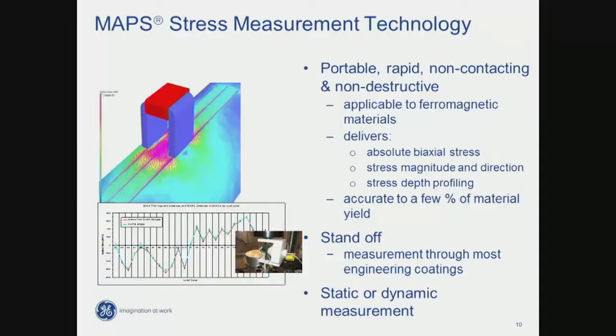Okay, so I've got one slide on what the technology does, and then I'll just flip straight into what we're doing for flexible pipe. So what we do is we measure stress. So M is magnetic, it's a magnetic technique. We measure stress on ferromagnetic materials, so a magnet needs to stick to it. And it's an absolute measure, and we deliver megapascals from that absolute measure.